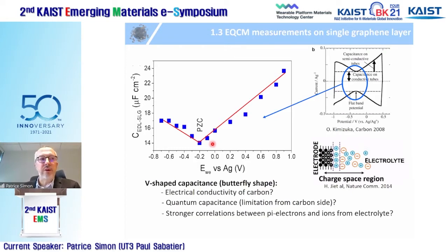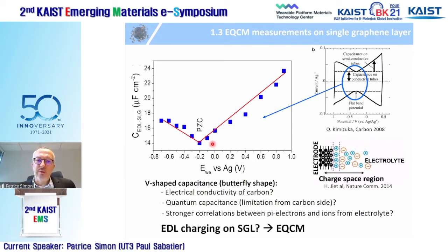However, there are other limitations which can explain this shape coming from the electrolyte: ion interactions in the electrolyte and interactions between the electrolyte ions and the carbon. So to try to understand whether it comes from the carbon or the electrolyte or both, we did some electrochemical quartz crystal microbalance study of that.